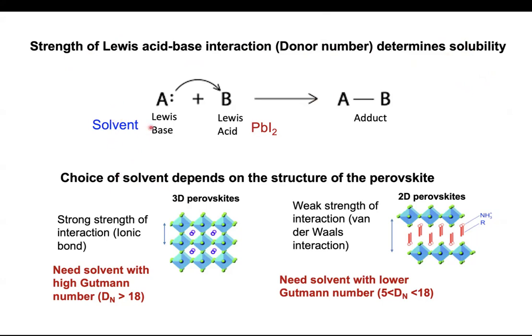For example, what I have is a solvent, which is a Lewis base, and then I have lead iodide, which is a Lewis acid. Okay. And typically, when you mix this, they form an adduct first, right? And then you form a perovskite. And now, depending on what solvent you choose, that depends on the structure of the perovskite.